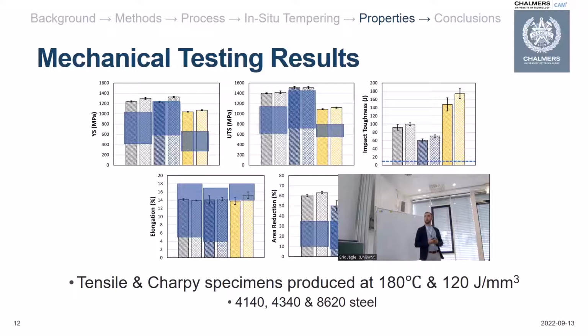And what was kind of more interesting was the impact toughness, specifically the Charpy impact toughness, where you're having, let's say, relatively high values for what would be considered a brittle material. And the other thing I want to quickly mention is when we start comparing the vertical and horizontal specimens, while there is directional anisotropy present, the level is much below the 10 or 20% that's usually mentioned in literature.